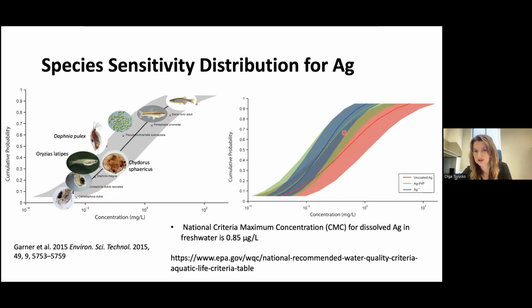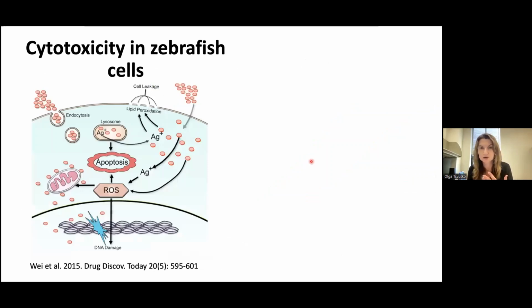However, if you look at species sensitivity distribution curves for particles that are, for example, coated, or for silver ions alone, then it's even steeper and there is even more toxicity. So the question is, when those particles are transformed, would they be dissolving or not? This is just the results of a study on zebrafish cells, to illustrate the toxicity of silver nanoparticles when they are taken into an organism and absorbed into the cells. Often they can dissolve before entering the cells and enter as silver ions, or they can be taken in through endocytosis and enter cells as silver nanoparticles.